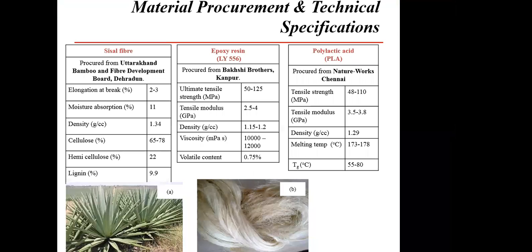Materials and method. I have taken sisal fiber as reinforcement, epoxy resin as a polymer, and polylactic acid for coating purposes for surface modification of the fiber. You can see the image. A is the plant of sisal fiber, and B is the sisal fiber after the retting process and mechanical method. This fiber is used as reinforcement, which is obtained from these plants.